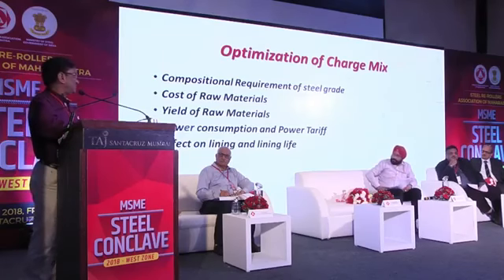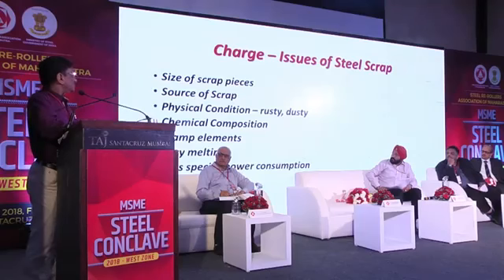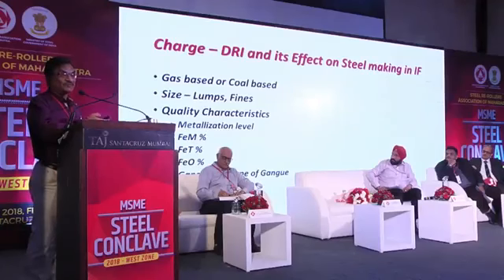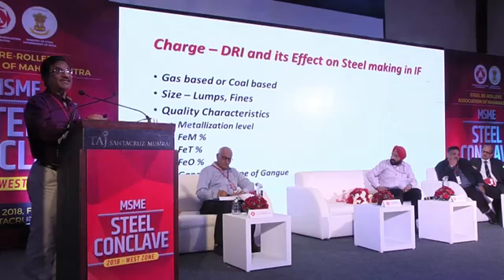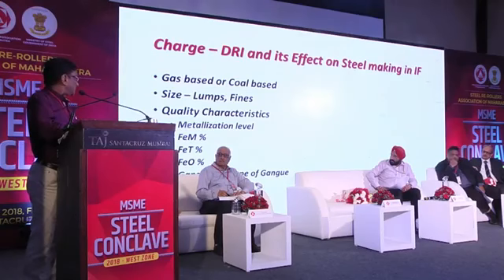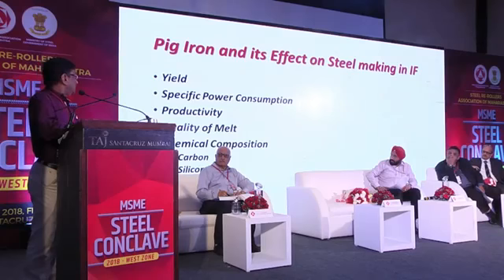Effect of lining and lining life. Very important. Issues of steel scrap, various issues, but you have to do the analysis. Techno-commercial analysis, always. DRI and its effects on steel making, like whether it is coal-based or gas-based. Gas-based DRI is always at a premium of 3,000 to 3,500, 4,000 rupees per ton. But still some plants use gas-based sponge iron because of techno-commercial analysis, it may be possible that yes, that works. Size, then quality characteristics, yield, specific power consumptions, productivity, quality of melt, all these factors I must analyze.